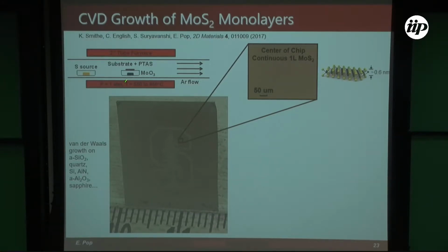The growth temperatures recently we've been able to reduce down to 550 Celsius. 550 Celsius is good because if you remember my talk from 2 days ago, I was arguing that industry really wants us to be below 500 to take this more seriously, right? And so we're trying. I'm not sure if this is actually the right way to do it. Maybe ALD growth is better, but this is what we have currently available, and so it is what it is.